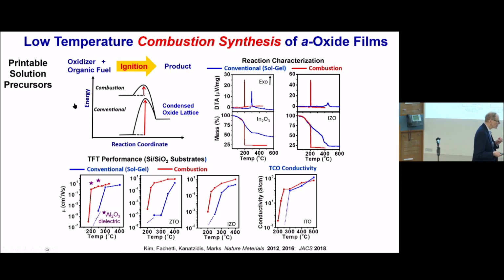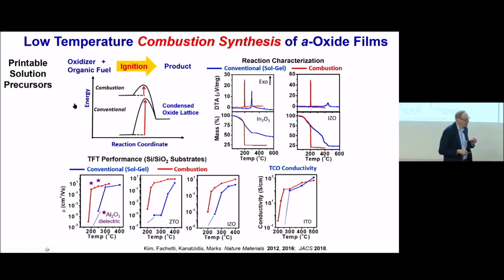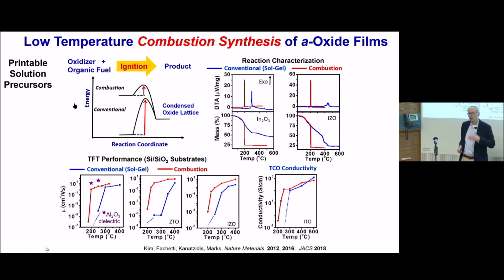The other thing is, if you really want to do this, Samsung, in terms of the IGZO that they sputter, uses giant, million dollar sputtering machines. It takes about 30 or 60 minutes to do a very simple IGZO layer. We developed it, and this is Myung-Gil Kim.